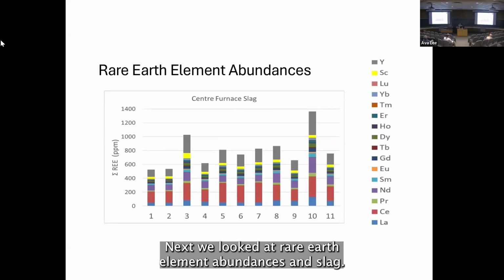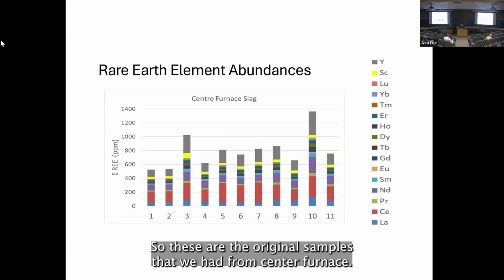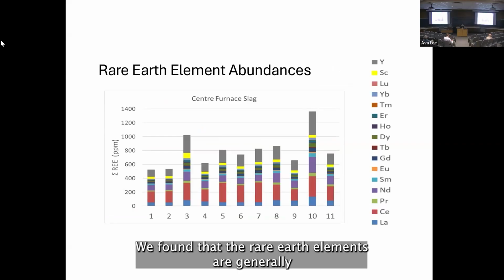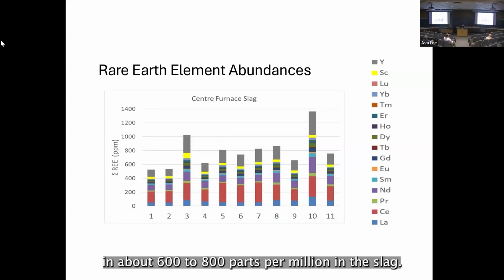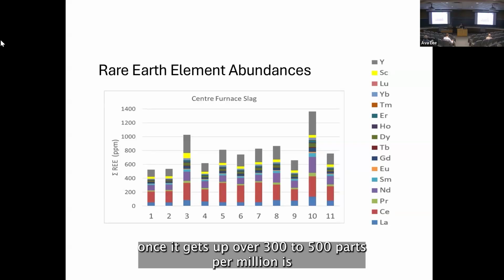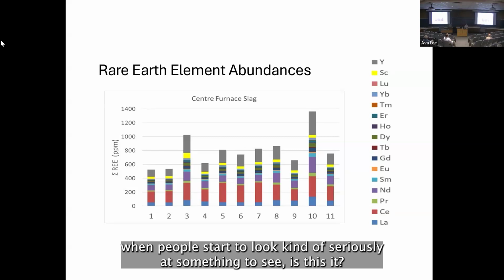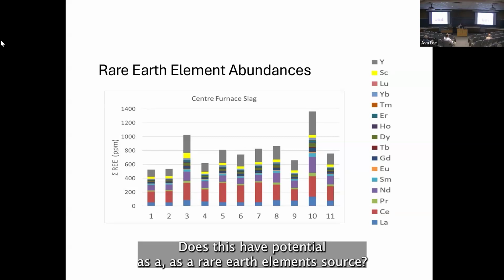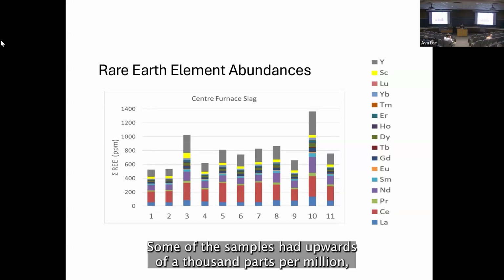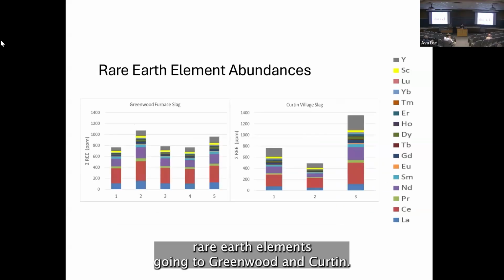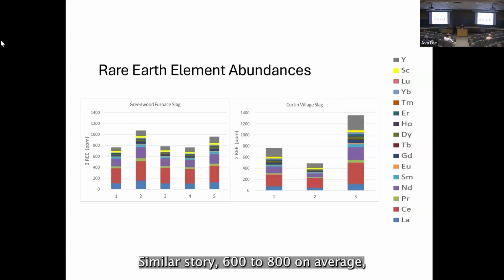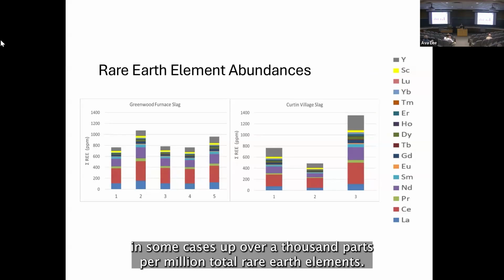Next, we looked at rare earth element abundances in slag. These are the original sample set we had from Center Furnace. We found that the rare earth elements are generally about 600 to 800 parts per million in the slag. As a point of reference, broadly speaking, once it gets over 300 to 500 parts per million is when people start to look seriously at something to see if it has potential as a rare earth element source. Some of the samples had upwards of 1,000 parts per million of rare earth elements. Greenwood and Curtin tell a similar story, 600 to 800 on average, in some cases over 1,000 parts per million total rare earth elements.